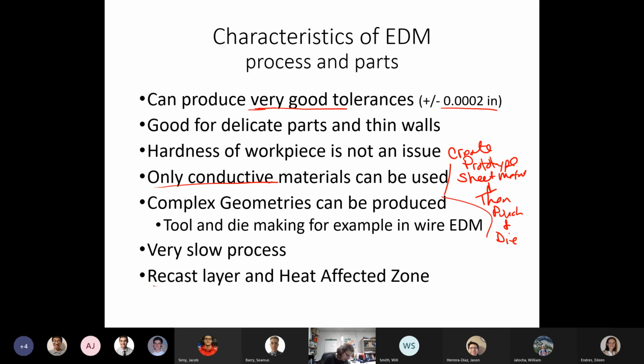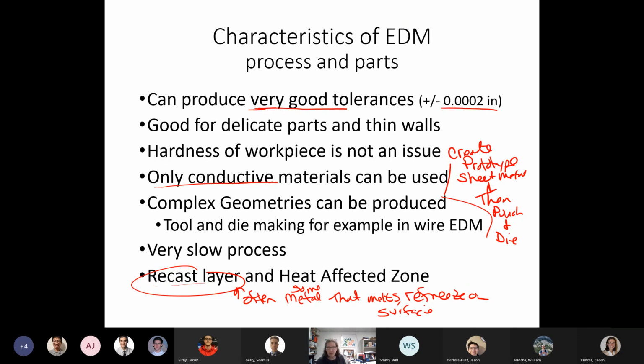There also is an issue with a recast layer and heat affected zone. With this recast layer, we often see that some metal that melts will refreeze on the surface. This is not great. There is some degradation or some loss of mechanical properties. Oftentimes that recast layer is just removed.